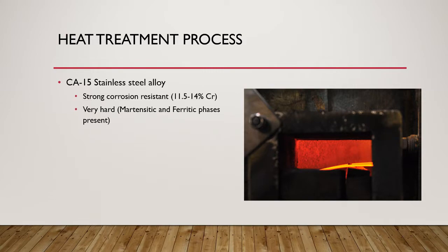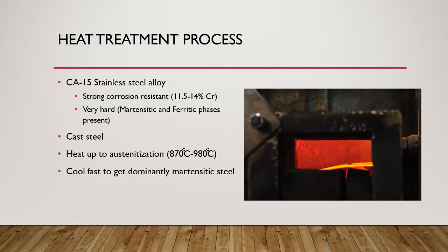So this steel is a stainless steel alloy with strong corrosion resistance, and is very hard, which is very good for our purposes. It starts out as a cast steel, and it is heated up to austenitization, which is around 800 degrees Celsius, and then it gets cooled very fast, quenched, to get dominantly martensitic steel, and then is tempered at 315 degrees Celsius to make it more machinable and stronger.